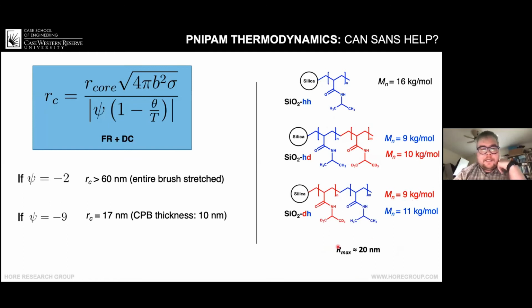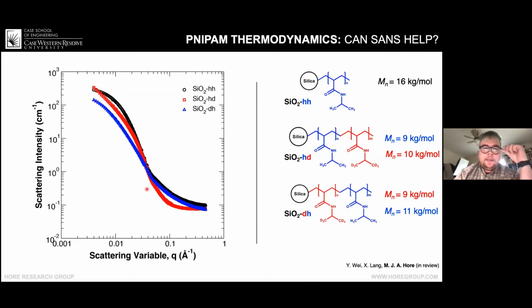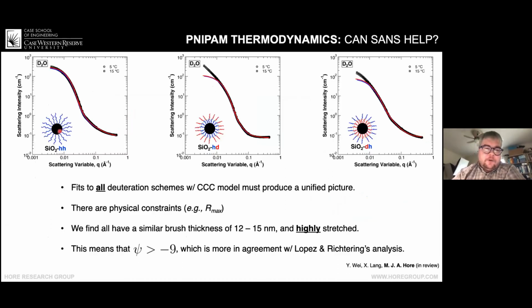And so this allows us to test whether or not one of these conditions is true. So you can see again, just by changing the isotopes in the brush, you get significantly different scattering patterns, and this gives us an opportunity to analyze these to come to some kind of result here. So we used the same models before, and I'm showing schematically what the different deuteration schemes represent. But at the end of the day, we measure these at 2 temperatures, 5 degrees and 15 degrees.